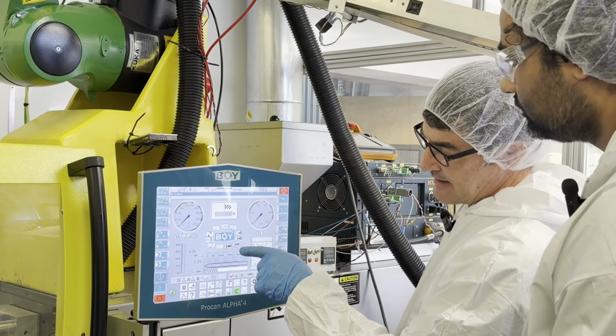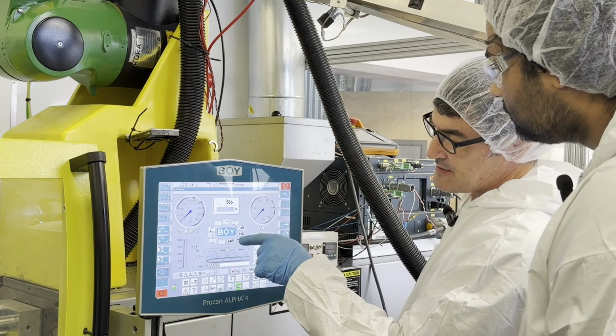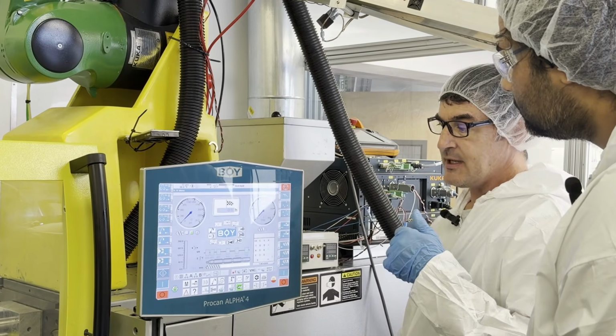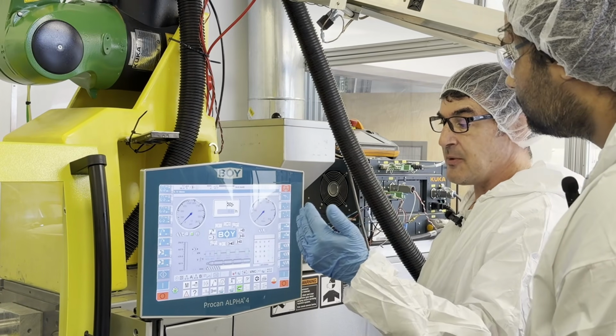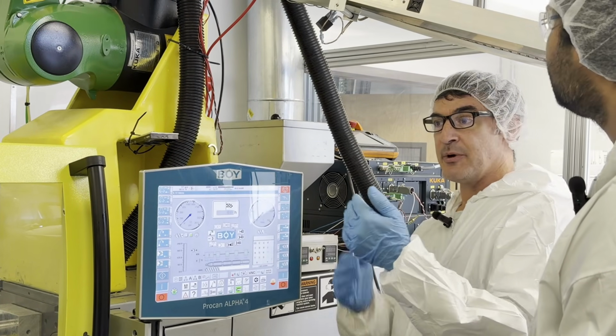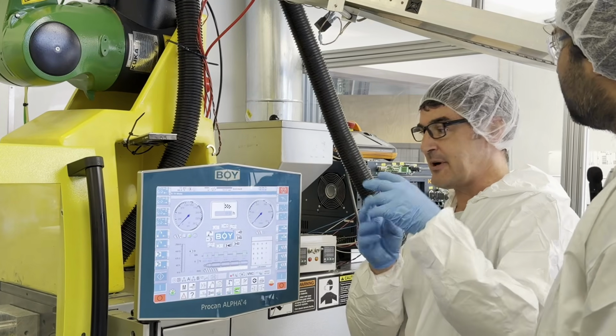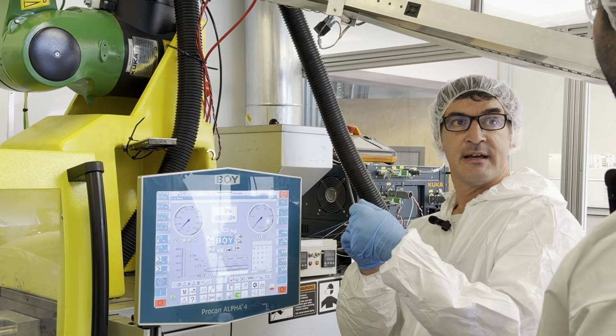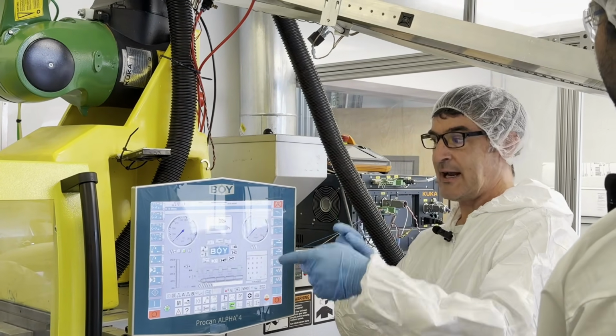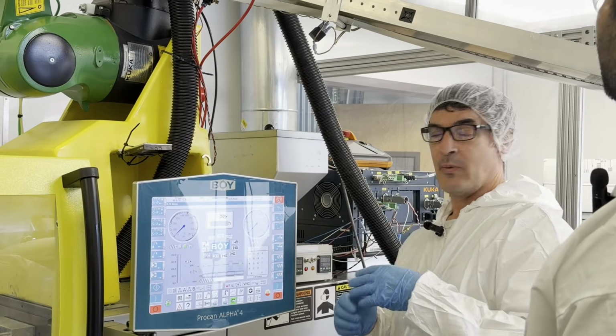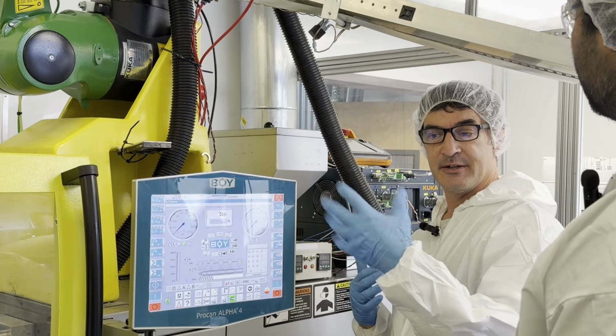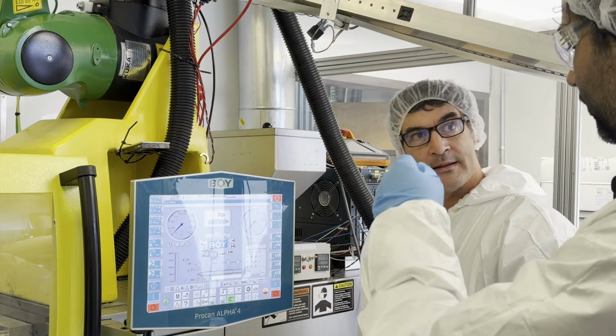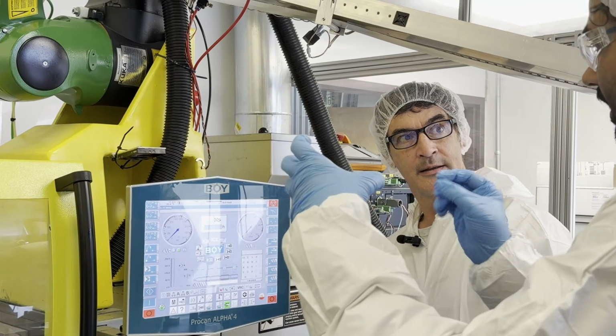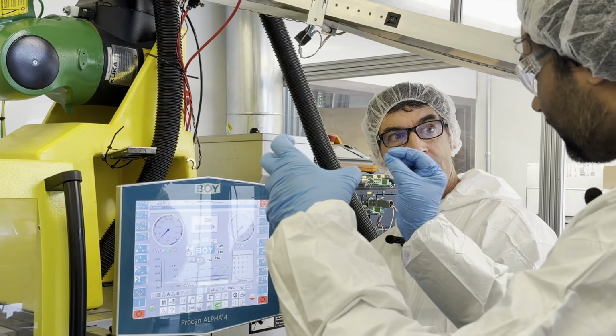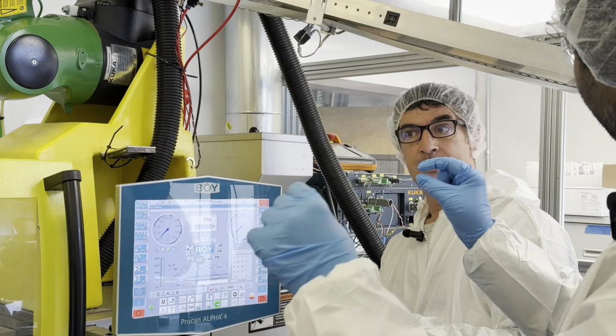The next step after that is the screw auger in the injection unit, if you choose to, will suck back a little bit, and that will pull some of that hot plastic away from the nozzle orifice. And that will help prevent that hot plastic from drooling out while the mold opens and you're ejecting your part. So hot plastic drooling out is like sometimes you see on a plastic there's a bump or there's like a streak there. That is the hot plastic drooling out?